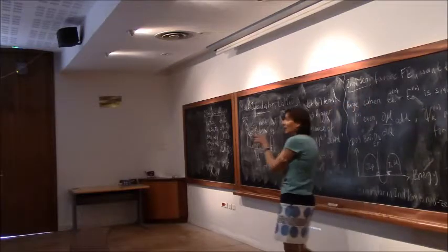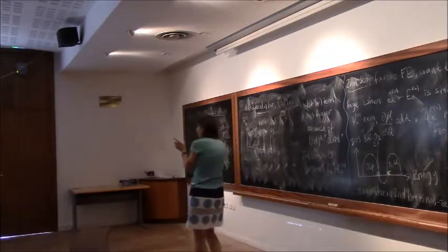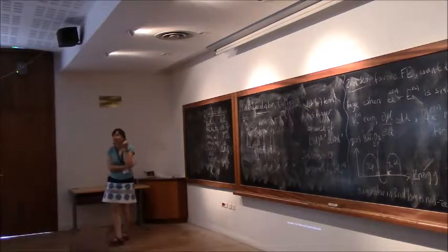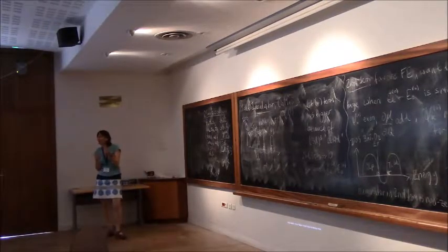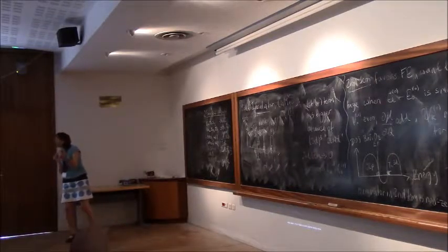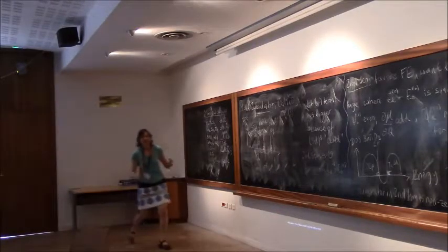Now again, it's a balance between these two terms. So it's not the case that calcium manganite is not allowed to be ferroelectric. In fact, if you strain it, at least in the computer, it becomes ferroelectric. I don't think this has been done in experiment. Does anybody know? But when I strain calcium manganite in my computer, I can make it ferroelectric, because I can tip the balance between these terms.